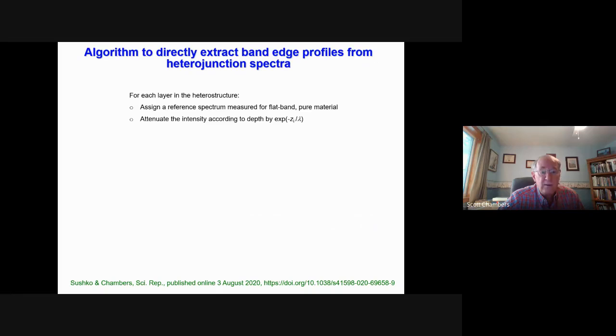So what we did was to develop an algorithm that would allow us to extract the band edge profile from the heterojunction spectrum. And in outline form, the way this works is the following. For each layer in the heterostructure, we assign a reference spectrum that's measured for the pure material in a flat band state. We assign that spectrum to each layer. We attenuate it according to its depth. And so we start off with a family of spectra like that, all at the same binding energy.